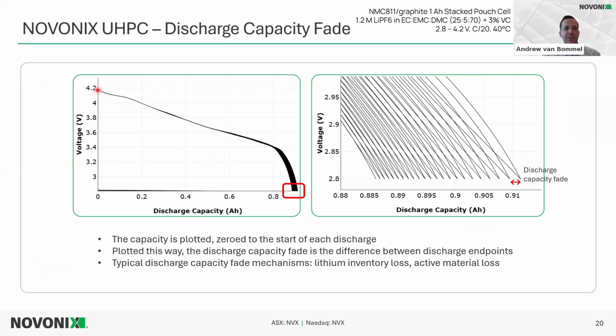Here we're zeroing the start of the discharge curve, and we see that each discharge just gets smaller and smaller. At the beginning, if we zoom into that area, the first discharge is a little bit above 0.91 amp hour for the cell, and at the end it's below 0.89 amp hour. The fade rate is the difference between that discharge capacity and the next one, so this would be N and then N plus 1. That would be the discharge capacity fade. Some typical reasons why we have discharge capacity fade are lithium inventory loss and sometimes active material loss as well.